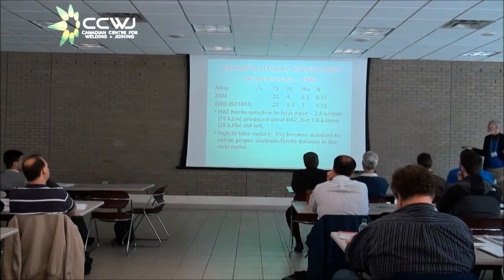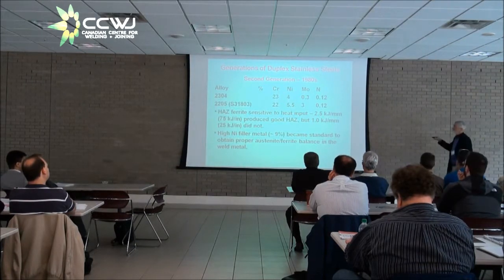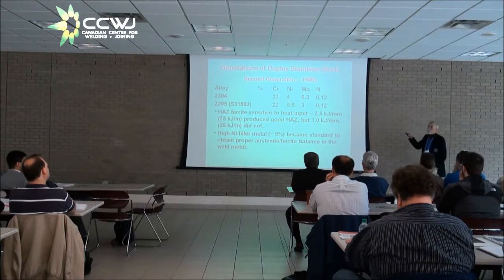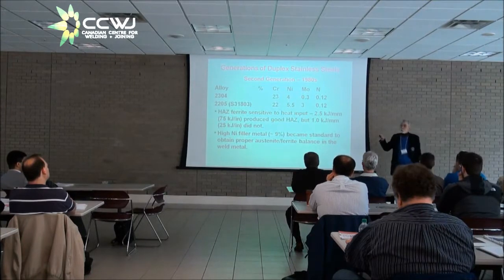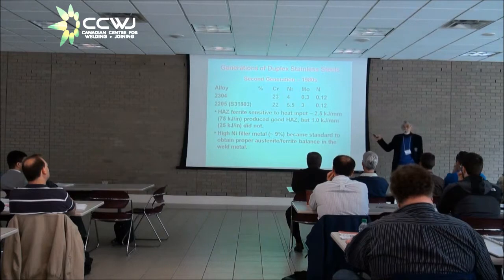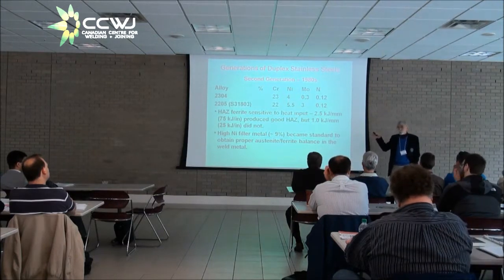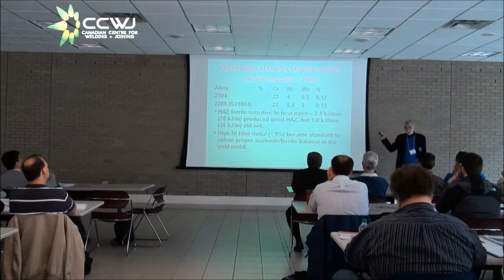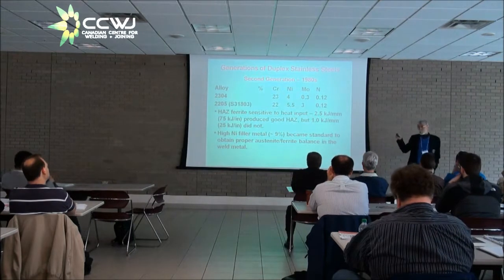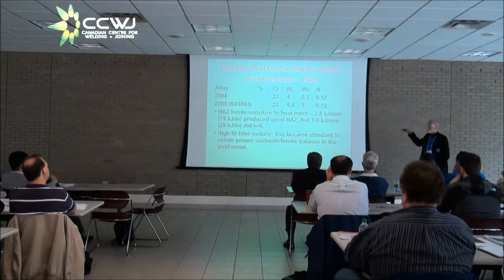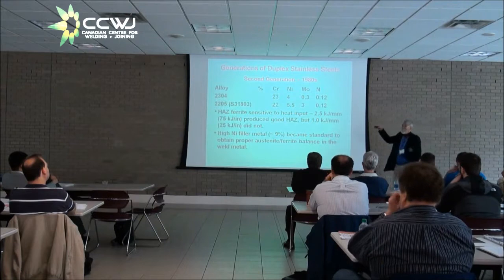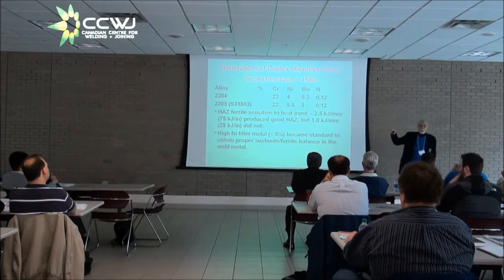With 12 points of nitrogen in them, the heat affected zone was now somewhat sensitive to heat input. If you had high heat input, you would get good heat affected zone properties. If you had low heat input, you would not get good heat affected zone properties. It all depended on how much time at temperature the material had in order to produce a decent amount of austenite.